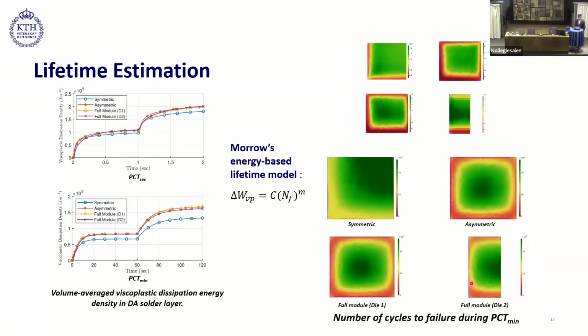If we look at during the PCT-min, then the lower number of cycles to failure distribution is uniformly distributed around the edges. So from this study, we concluded that the location of the die inside the package and also depending on the number of dies we have in parallel, the reliability of the solder material we used inside the package varies.